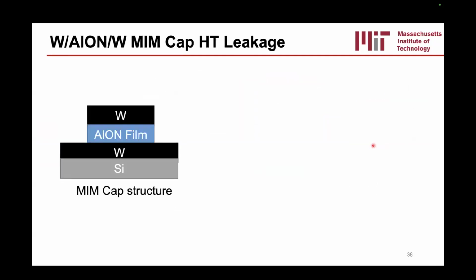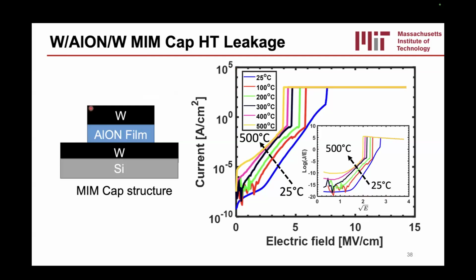Additionally, we wanted to make sure that this film is actually insulating at high temperatures. So we made some tungsten aluminum oxynitride MIM capacitors, and we measured the current and voltage characteristics. In this case, current normalized to the area and the electric field normalized to the thickness of the film from 25 Celsius to 500 Celsius. And we can see that the critical field drops a bit from about 7 to 8 megavolts per centimeter to 4 megavolts per centimeter, but it's still a relatively insulating material, and 4 megavolts per centimeter is bigger than the electric field of gallium nitride, and so we're happy with that.